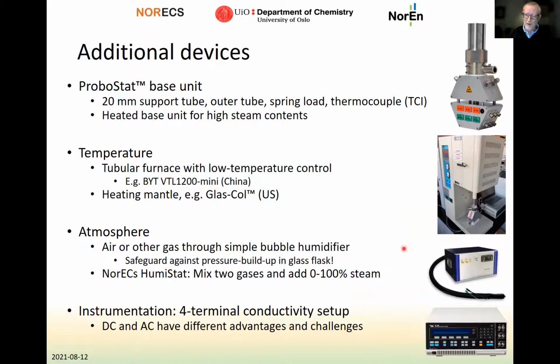You need to control the atmosphere. You need to control the humidity. So you can do this by sending air or another gas through a simple bubble humidifier. You must take care to avoid the pressure buildup in such bubblers. Or you can, for instance, get a humistat from Norecs, which is a machine that can mix two gases in any ratio, and in addition add from 0 to 100% steam through a heated tube that goes to the ProboStat. You need instrumentation. You need something that can measure with a 4-terminal setup.